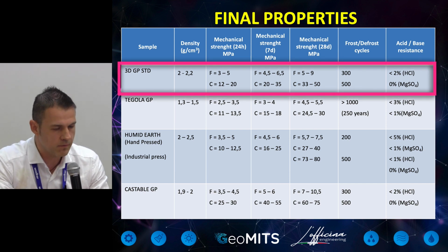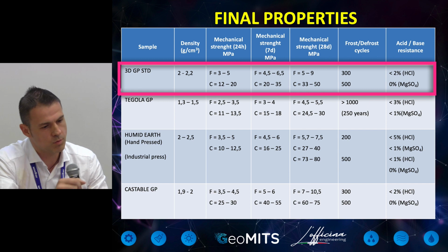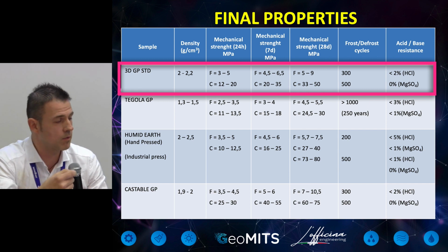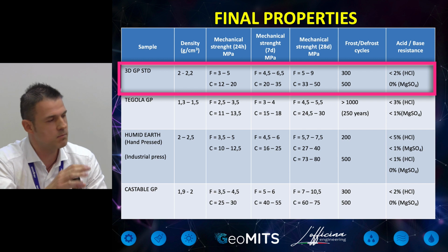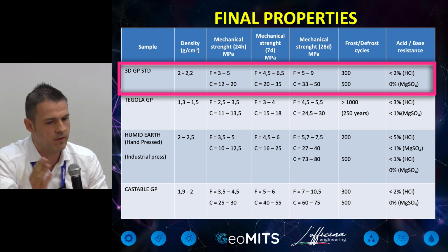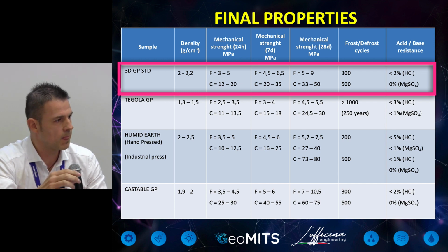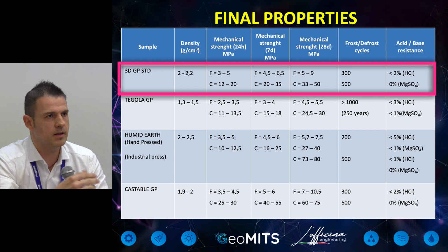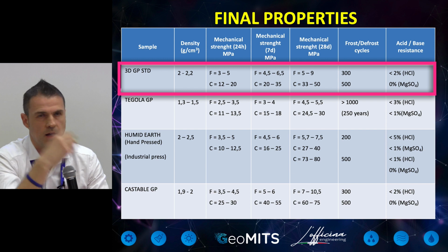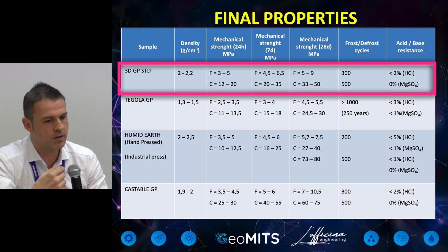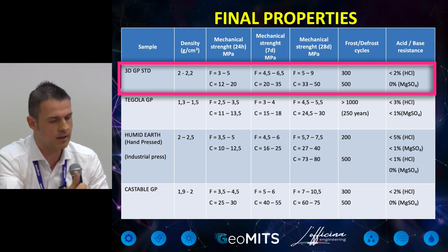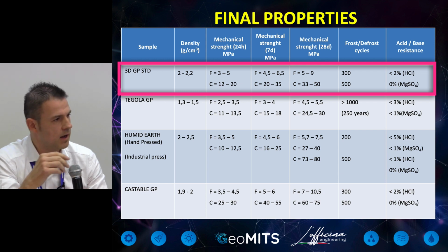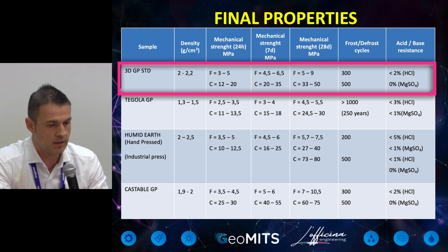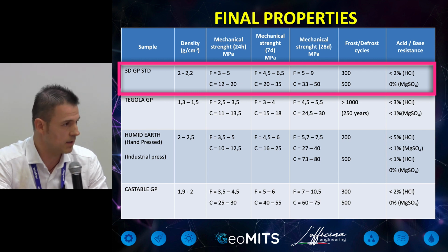So for 3D GP, the density can change from 2 to 2.2 depending on the type and the quality of aggregates, because I use the same binder with different aggregates. The lower results are obtained with standard sand, silica sand, because every time we made the testing, every client has quartz or silica sand because it's cheap, because it's at disposal worldwide. But I prefer to use feldspar rock, so the highest data are obtained with feldspar rock that are also quite cheap or cheaper than quartz.